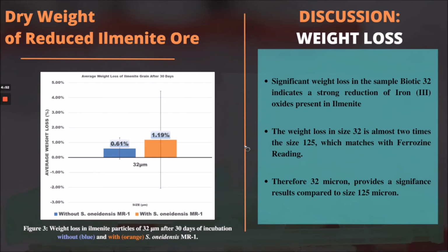The weight loss test was selectively done on 32 micron ilmenite particles due to the impeccable iron leaching seen in the Ferrozine test earlier. As expected, the weight loss difference between the untreated blue bar and the Shewanella-treated orange bar is almost 2 times. In a nutshell, Shewanella reduced the iron to its soluble form in the media, thus reducing the weight of the ilmenite grains.